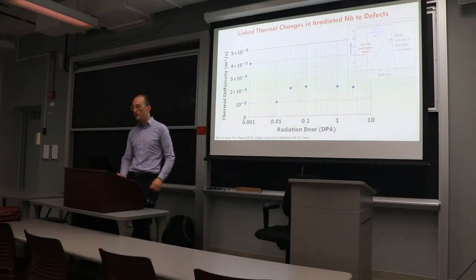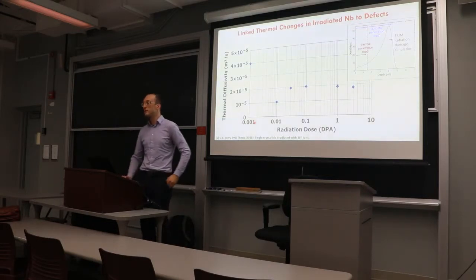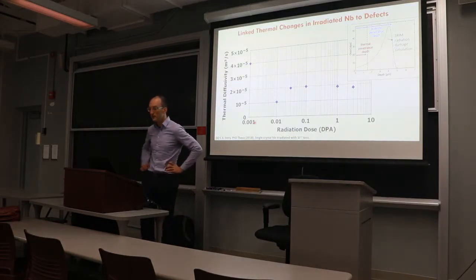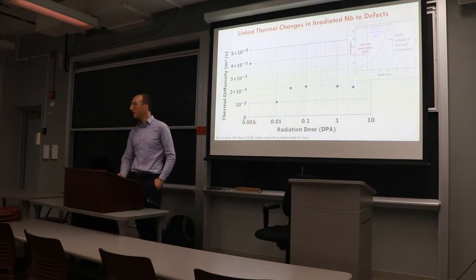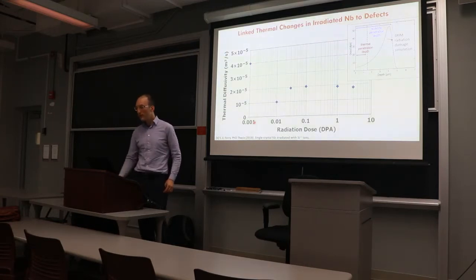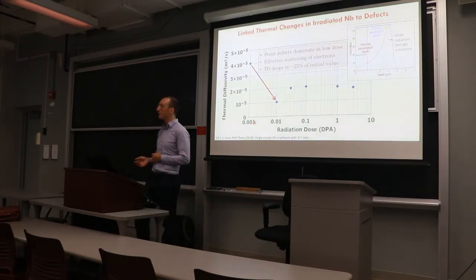We first looked at things like perfect single crystal niobium and looked at their thermal diffusivity change as a function of radiation dose. Now these irradiations took like seconds because of the silicon ion irradiation. It does not take long to get to 0.001 dpa. We actually had to design a circuit to quickly raster the beam because we couldn't blank it fast enough to get this low of a dose. And we see that at a very low dose, the thermal diffusivity plummets by a factor of 4.